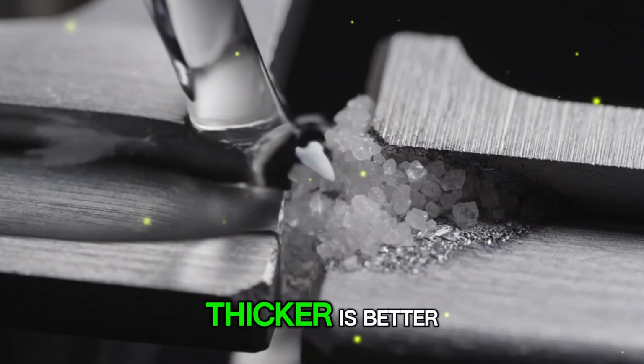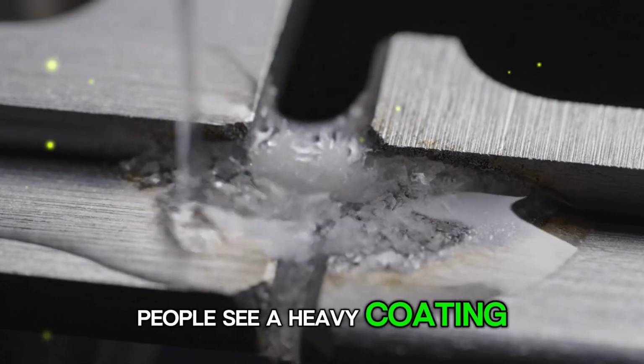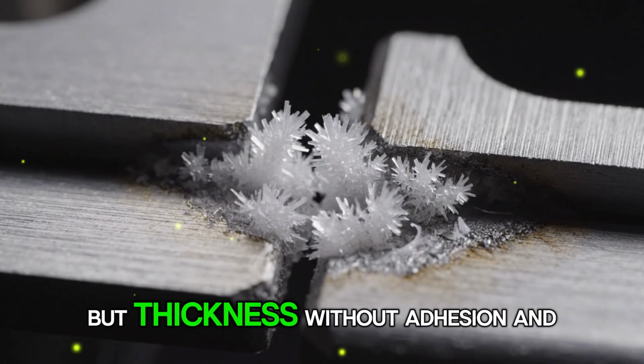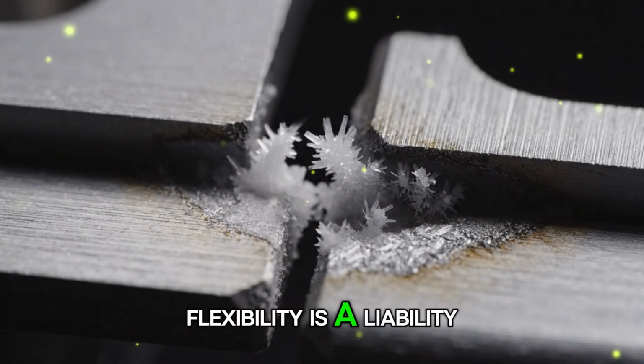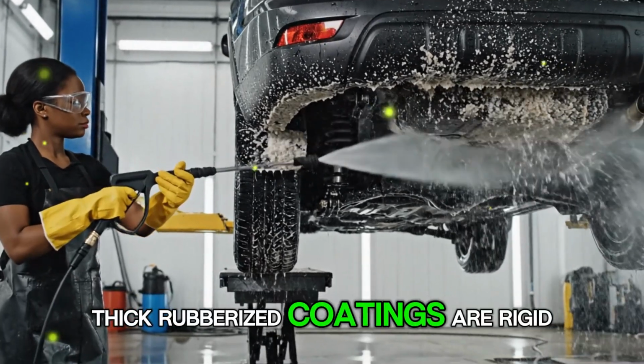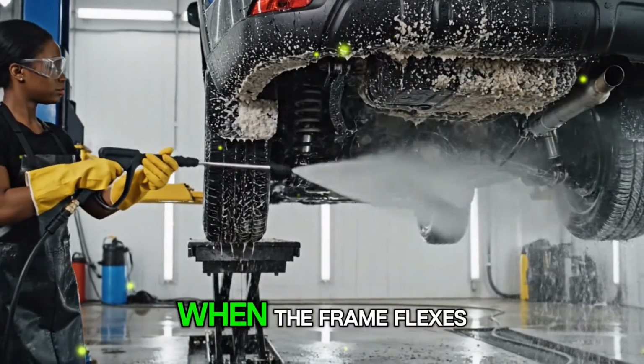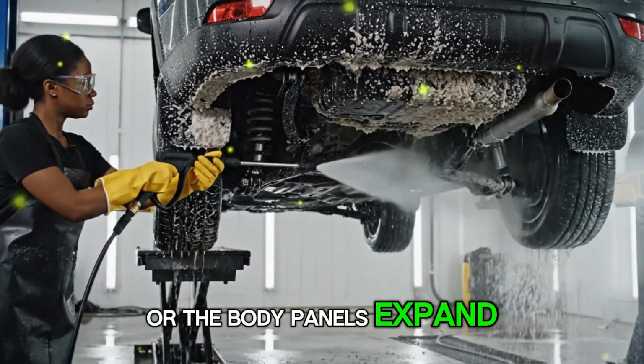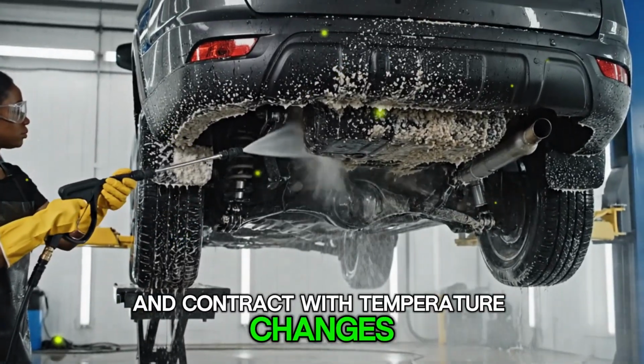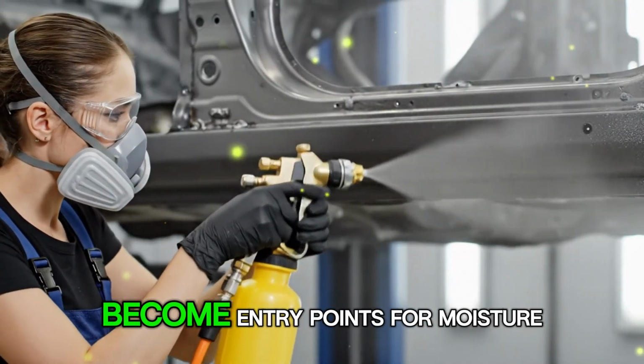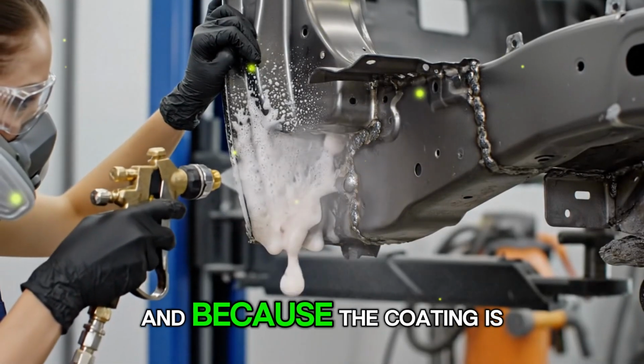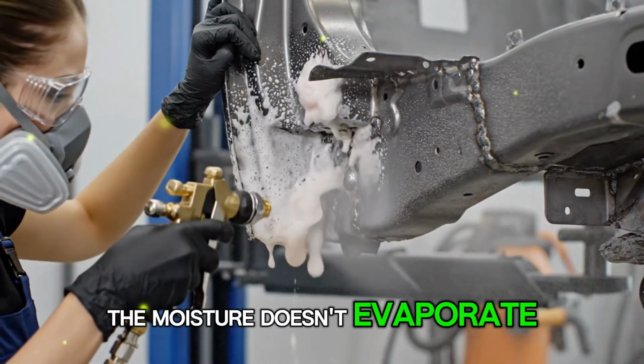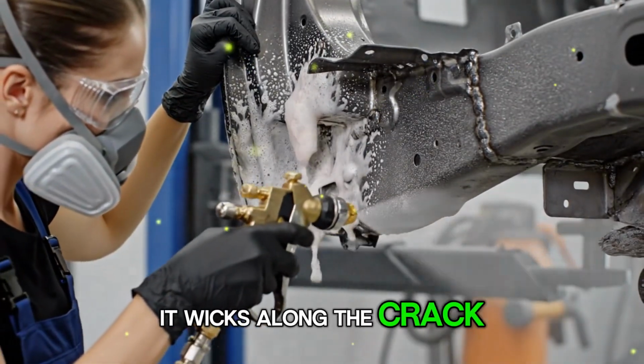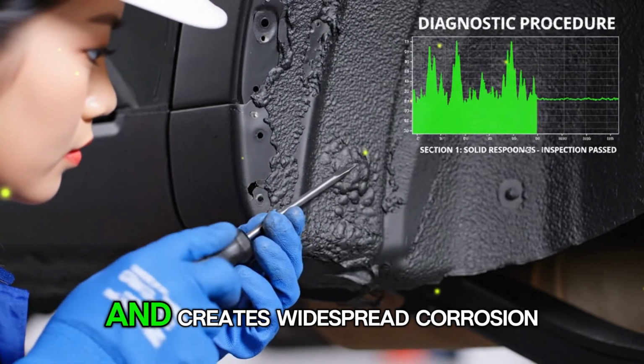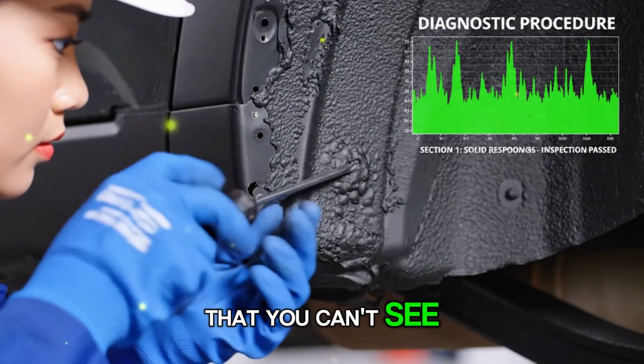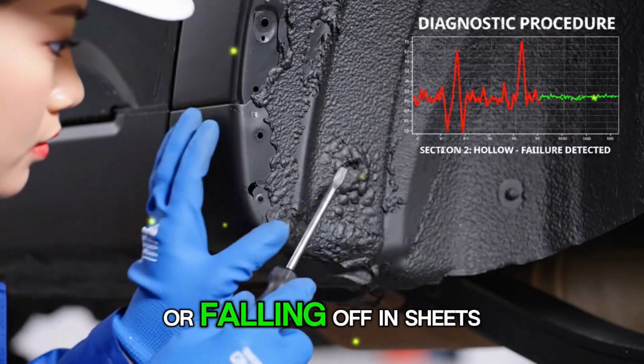Then there's the myth that thicker is better. People see a heavy coating and assume it's more protective. But thickness without adhesion and flexibility is a liability. Thick rubberized coatings are rigid, they don't move with the metal. When the frame flexes or the body panels expand and contract with temperature changes, thick coatings crack. Those cracks become entry points for moisture. And because the coating is thick, the moisture doesn't evaporate. It wicks along the crack, spreads laterally under the coating, and creates widespread corrosion that you can't see until the coating starts bubbling or falling off in sheets.